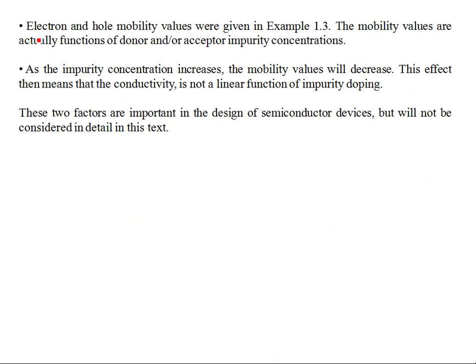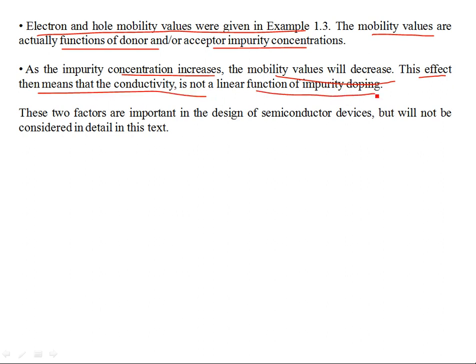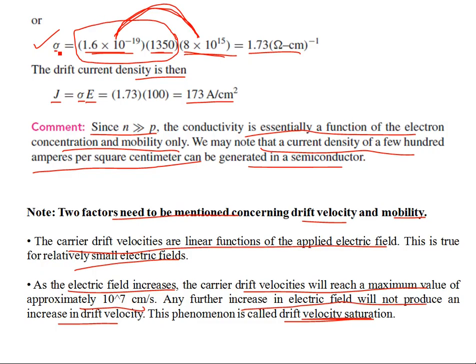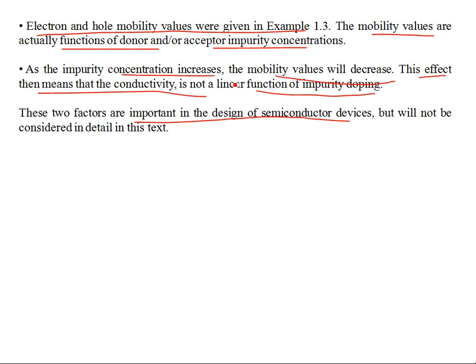Now, the electron and hole mobilities, whose values were given in the previous example 1.3, constitute the conductivity of the material. The mobility values are themselves a function of donor and acceptor impurity concentrations. As the impurity concentration increases, the mobility decreases. This secondary effect means that the conductivity is not a linear function of impurity doping. These two factors are important in the design of semiconductor devices. Yes, the conductivity depends on the amount of charge and the mobility of the free charge carriers in an N-type or P-type material, but if you keep increasing the impurity concentration, the mobility also decreases.